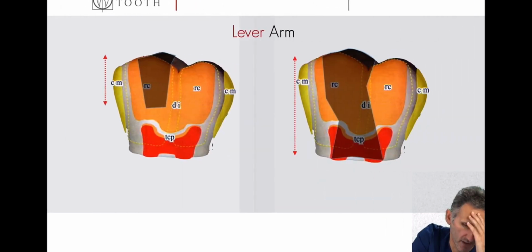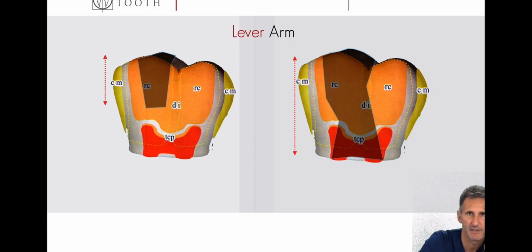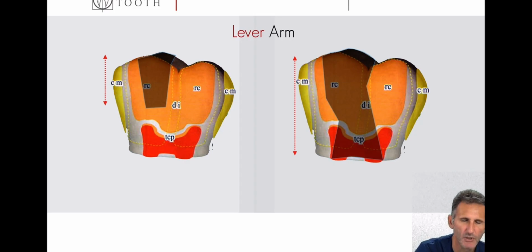And so, if we have an endodontic treatment and we have the lack of the ceiling of the pulp chamber, the lever arm is increased. In the same way as the branch, if the branch is much longer, I am able to flex much more. Doing this, the accumulation of fatigue will be quicker and the fracture will arrive sooner.